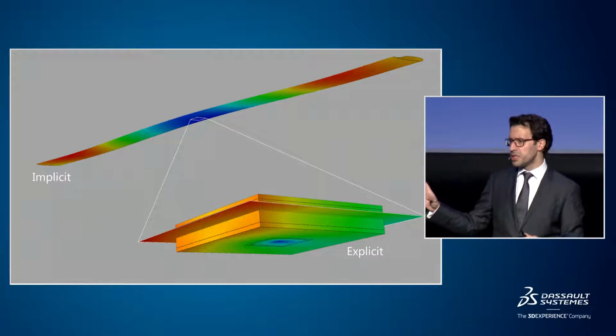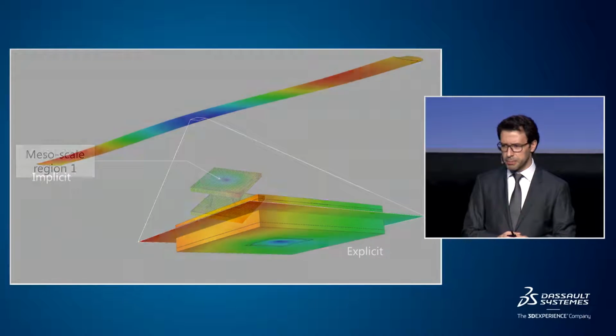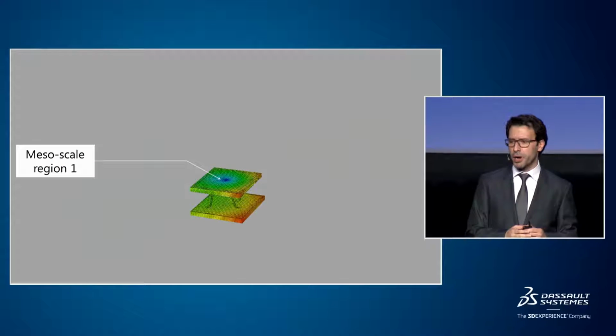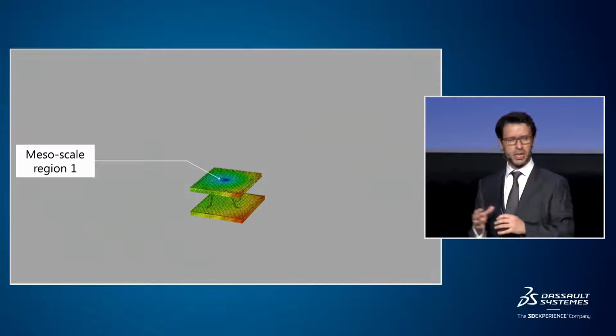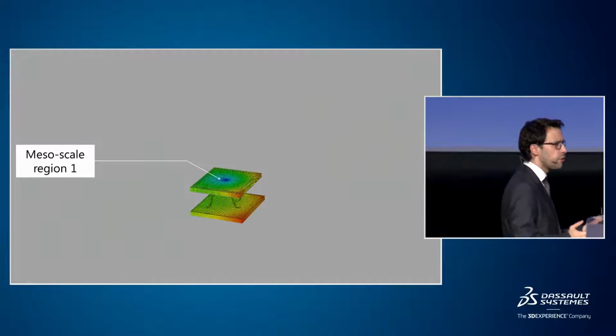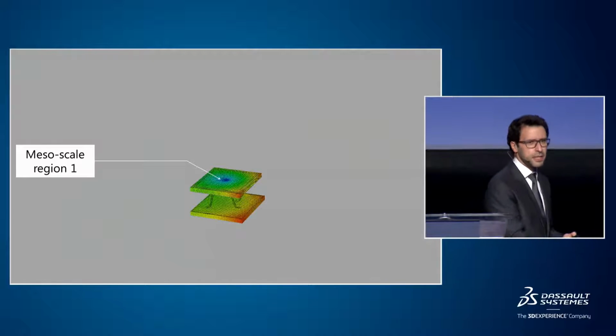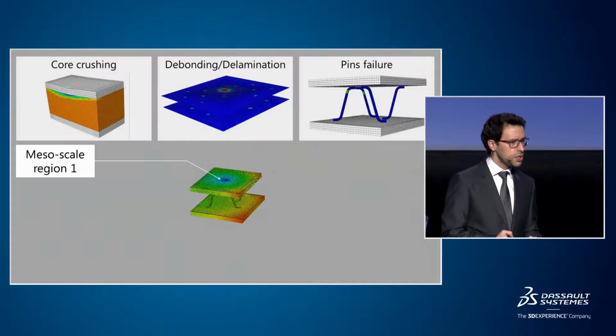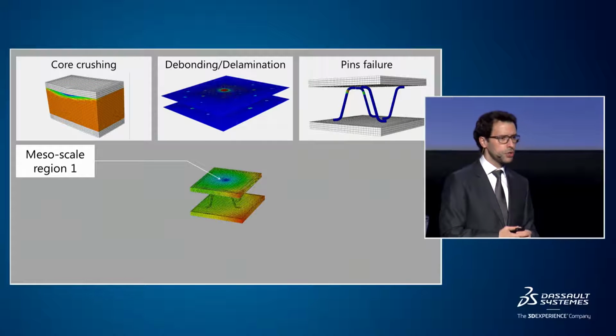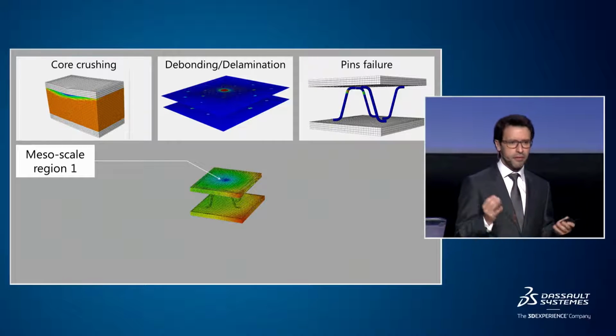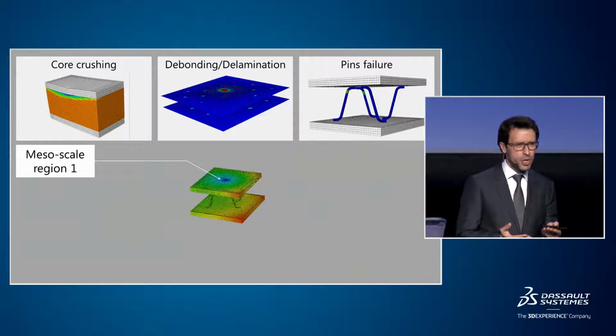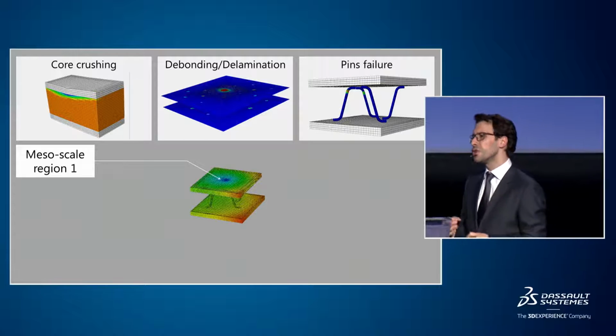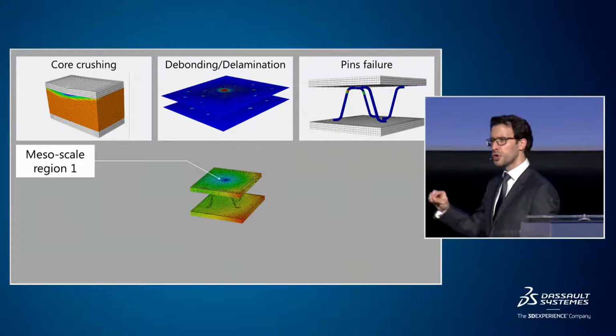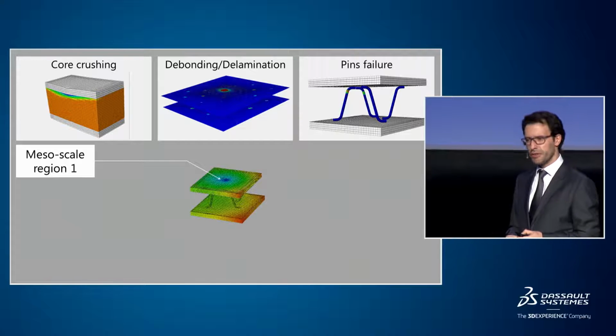Now I'll show you in more detail this refined region in explicit. It has a central part where, in addition to what you can see on the screen, there is also the foam. I'm not showing you the foam so that you can see the pins inside. And in this region, we are simulating the crushing of the core, the debonding between the core and the face sheets, and also the delamination between the different carbon epoxy plies on the face sheet, and crucially also the failure of the composite pins that bring the face sheets together.